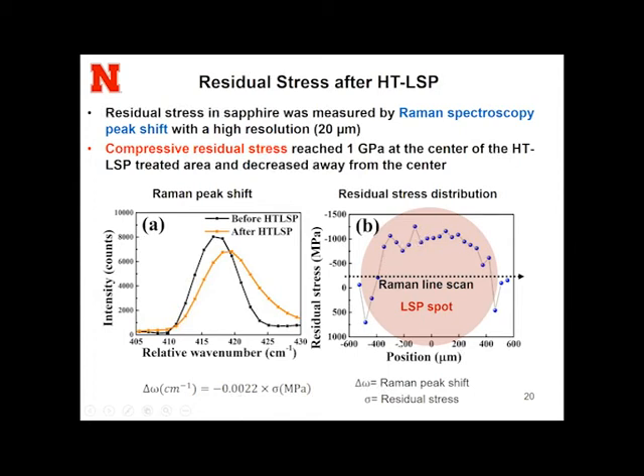And here, this is a laser shock peening spot, and we do a line scan of the Raman measurement. You can see in the middle of the spot, there is a significant 1 gigapascal compressive residual stress, which decreases when away from the center. On the edge, you can also see some tensile stress, which is to balance the compressive stress in the center. But anyway, we found in sapphire it can generate a very high compressive residual stress.